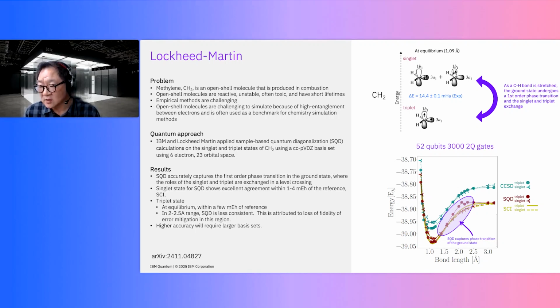And you can see, for example, that the CCSD approach, that simulation method, does not capture that phase transition. And you can also see that the SCI method also captures this phase transition. Qualitatively, you can see that the SQD method is capturing this phase transition. Quantitatively, at equilibrium, again around 1.1 angstroms, the triplet and singlet states are very close to the reference algorithm, the SCI state, and we're within a few millihartrees of the reference.